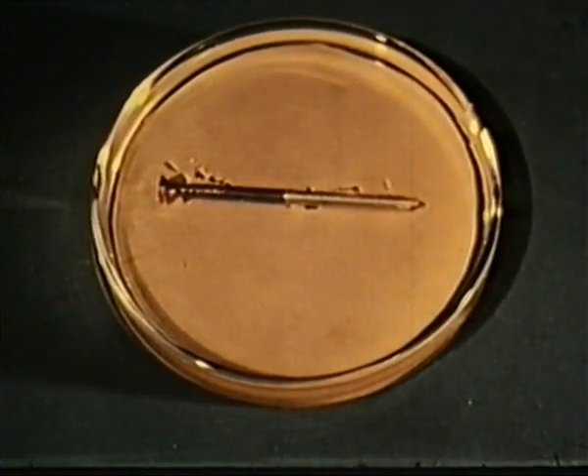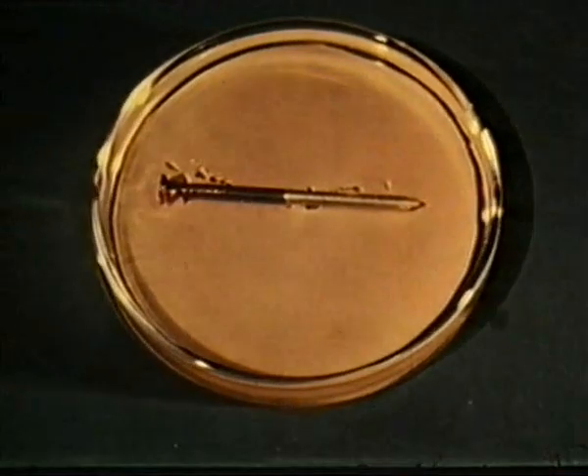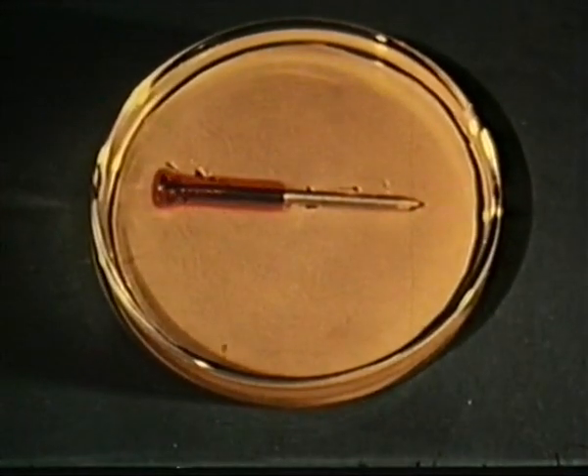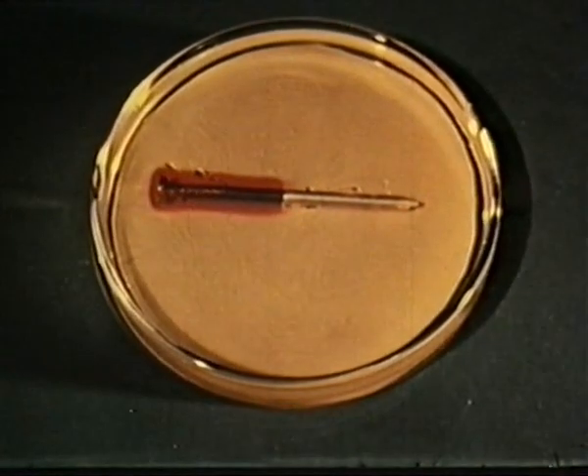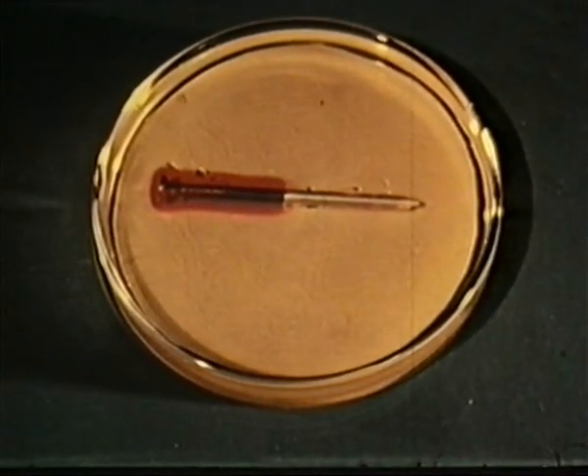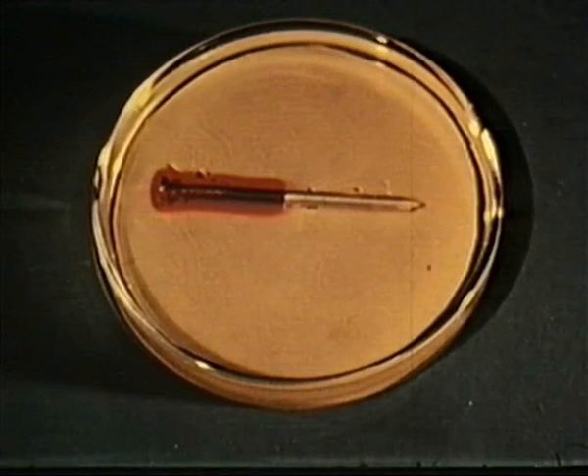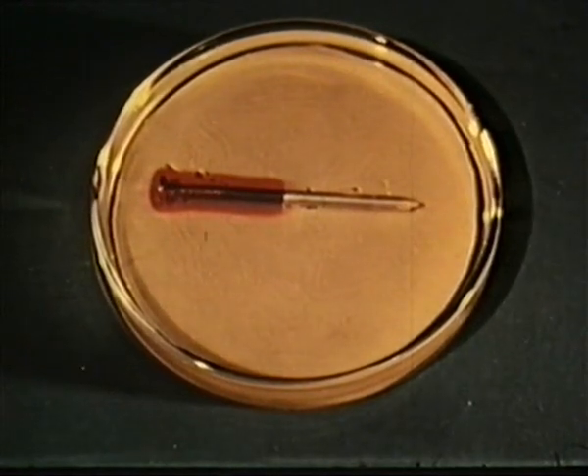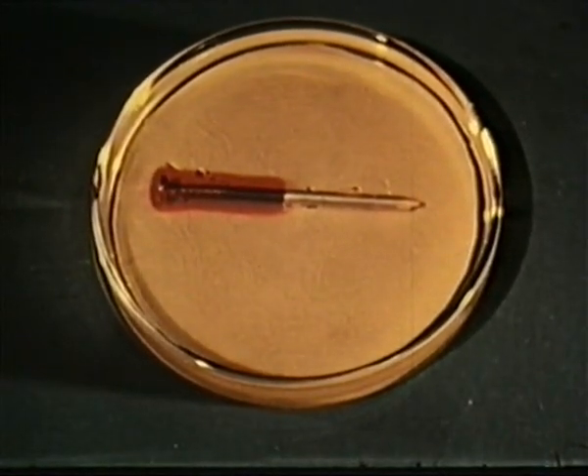Here we have an iron nail with the pointed end plated with zinc. We see now that the red color identifying the cathode develops at the iron half, where no iron goes into solution, and therefore no blue color develops. The zinc is corroding as an anode at the point and is consumed in providing protection to the iron. Since zinc ions do not develop a blue color with the ferrocyanide, there is no blue indication of an anode in this case.